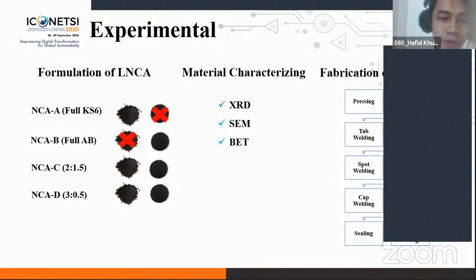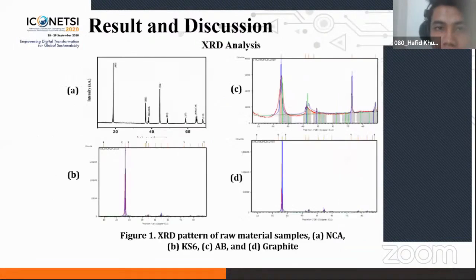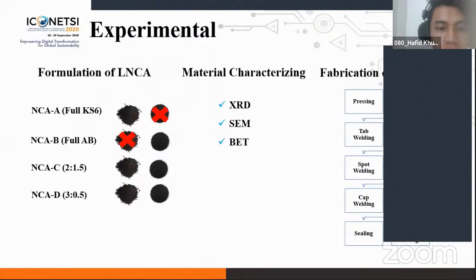Fabrication. Fabrication of the cylindrical cell consists of electrode coating, cylindrical assembly, and electrolyte filling. All of the starting materials of the cathode and anode were separately mixed in a vacuum mixer to get homogeneous slurries. Then the slurry was coated on the surface of the current collector. The cathode slurry was coated on aluminum foil, while the anode slurry was coated on copper foil using a Doctor Blade automatic coating machine. The coated foil was dried and pressed using a rotary pressing machine.